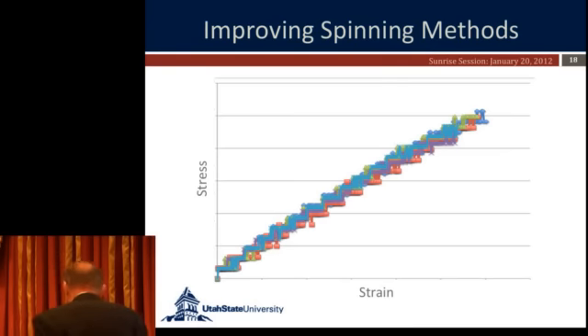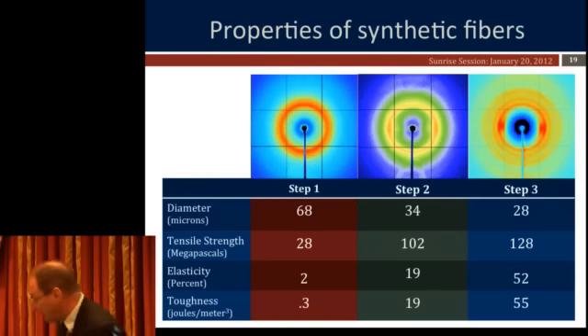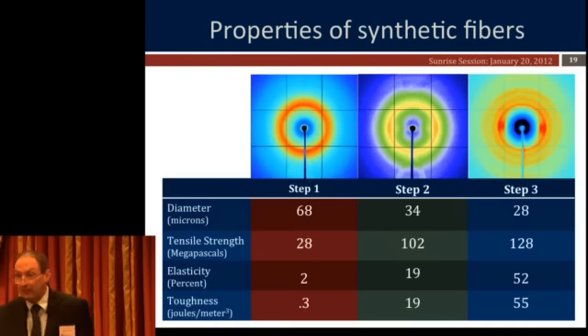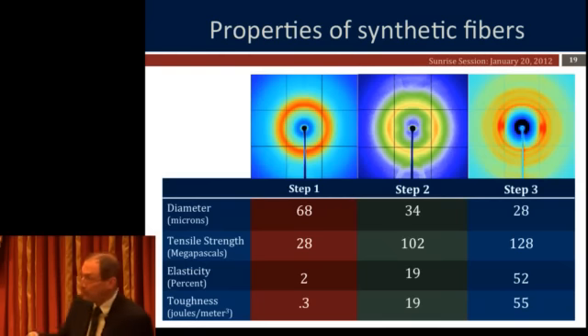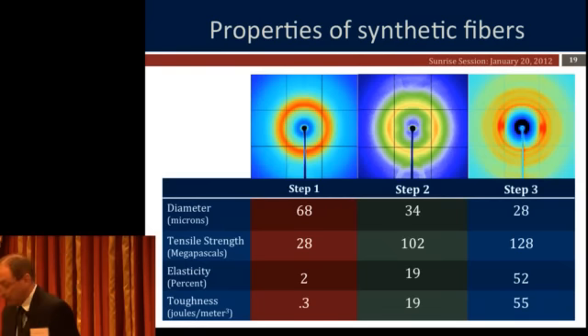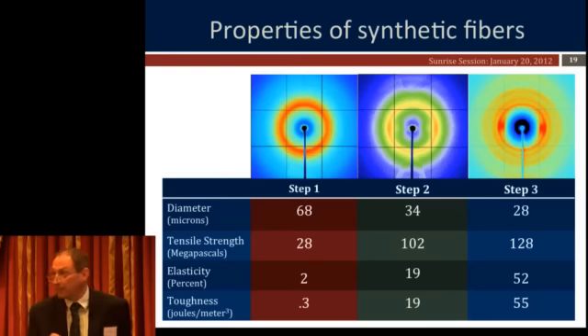So the problem is that when we get done with the spinning, they're still not very good. So what we learned was that if you stretch them in an alcohol water bath, they get much better. And if you then dip them in water and stretch them a little more, they get much, much better. So we looked at the structure of these, and we did it using both NMR, which is like MRI for small molecules, uses exactly the same principles, and X-ray diffraction, which is the same thing as taking X-rays, except again we're looking at small molecules, but the X-rays have much prettier pictures. The NMR doesn't have a very pretty picture.